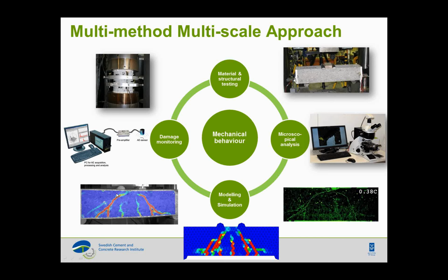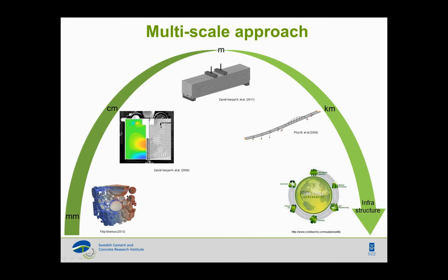Looking into different scales in this approach, it's quite important to realize that deteriorations actually start at the small scales, meaning that you have to have an understanding of what happens at the scale of aggregate cement here in this figure. And then from there you try actually to estimate, for instance, the chloride ingress through the concrete cover and so on. In a larger scale, we'll look into material properties of plain concrete. In this case, we're looking into a wedge splitting test, how corrosion induced crack is opened up in a wedge splitting test. Then we go to a scale higher up where we have a full bearing element.